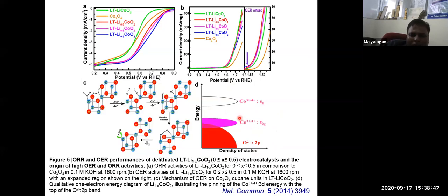What I'm saying is I want to replace platinum for the oxygen reduction reaction, and replace iridium oxide for the oxygen evolution reaction. When I remove lithium and change the chemistry, so that the Co3+/4+ and oxygen 2p overlap, this catalyst shows better performance. Delithiated low temperature lithium cobalt oxide, meaning lithium removed, shows better performance than the platinum and iridium oxide.